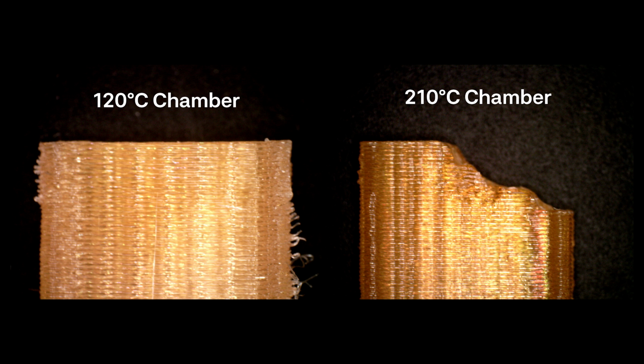By the time the part has cooled, the critical window for developing strong interlayer welds has already passed. In short, the best time to develop strong interlayer welds is during the printing process, not after the part has cooled. Looking at the fracture surfaces, we can see the consequence of poor welding firsthand. On the left, the ULTEM 1010 specimen printed in the 120C chamber failed perfectly along the layer boundaries. At the recommended chamber temperatures, fractures propagated through dozens of layers, showing that the interfaces were no longer acting as the dominant weak points.